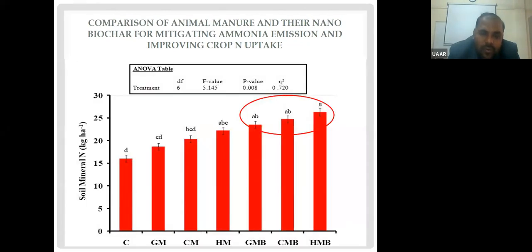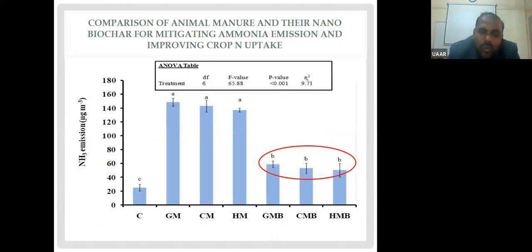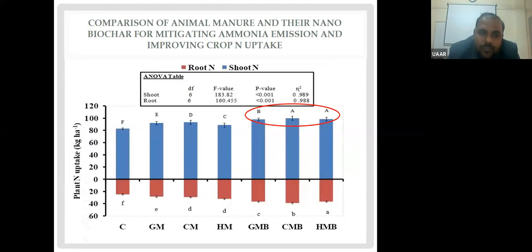kilogram nitrogen per hectare. And if you look at the results, by converting these manures into their NANOBIOCHAR, they have improved soil mineralization significantly, and also they have reduced ammonia emissions significantly. If you look at them, there was also no difference between these NANOBIOCHARs and between these manures, but compared with manures and NANOBIOCHAR, the ammonia emission was significantly reduced. Also, if you look at the plant N uptake, especially the shoot N uptake, it was enhanced by converting these manures to NANOBIOCHAR. So they were very effective if we only convert these manures to NANOBIOCHAR and then apply to the plants.